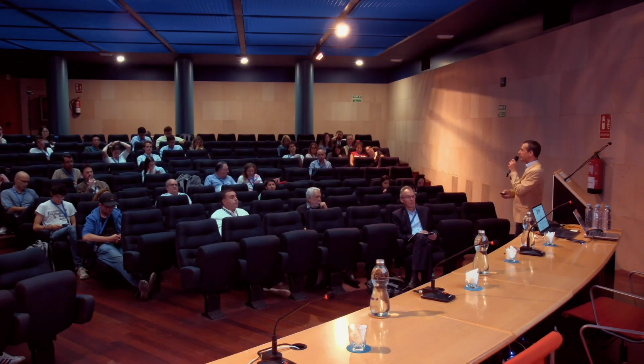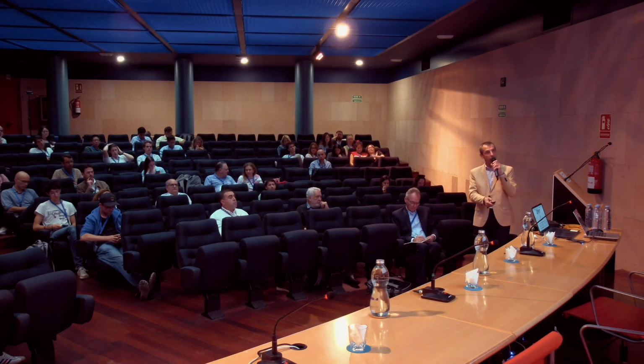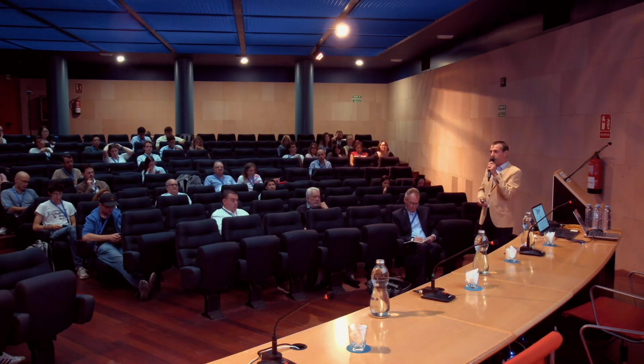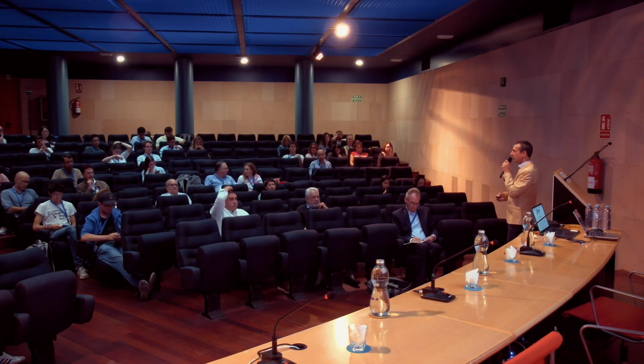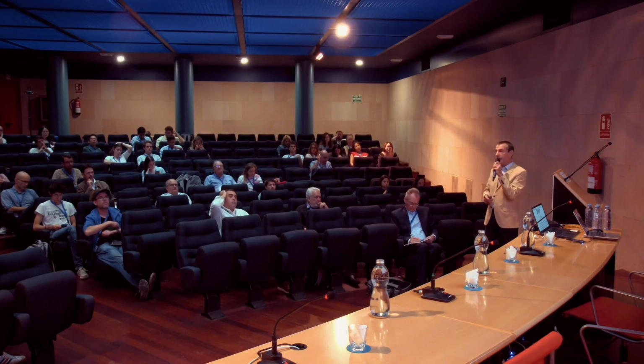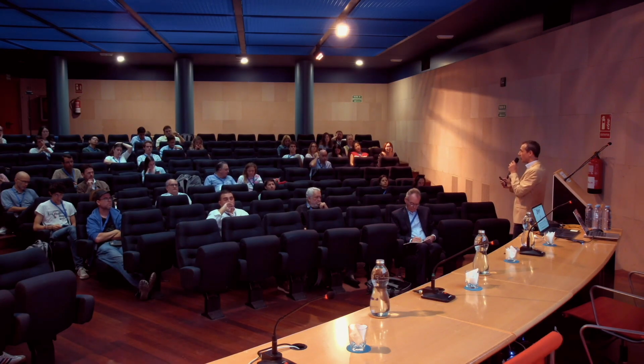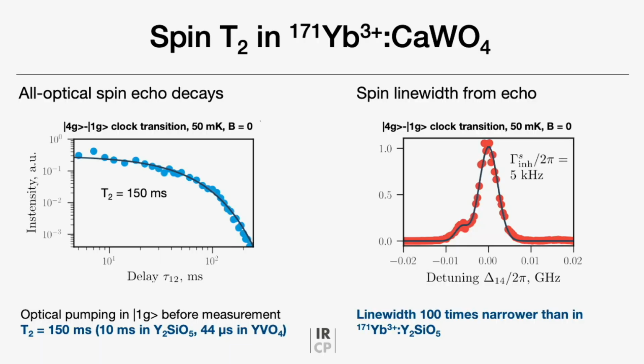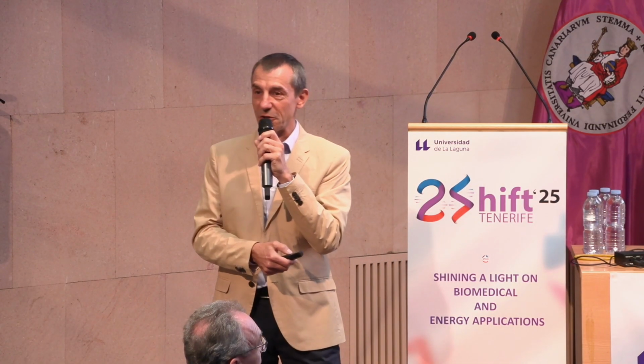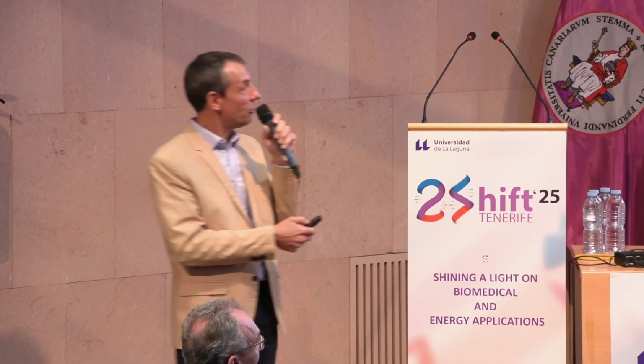So what does it mean, 150 milliseconds? Well, if we compare to other crystals, it's quite amazing, because another very popular host for ytterbium-171 that we studied before is yttrium orthosilicate, and in general, it's an excellent material for quantum applications based on rare earth ions. But you see that in YSO doped with ytterbium-171, we could have only 10 milliseconds. So we gain a factor of 15. And if we now move to yttrium vanadate, also with ytterbium-171, we have only 44 microseconds. So you can see that calcium tungstate is really an exceptional matrix for ytterbium-171.